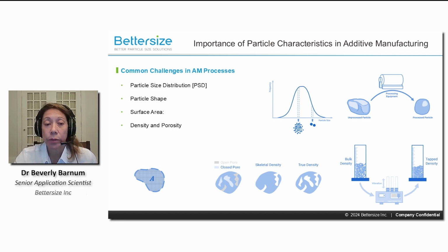The size of the powder particles affects the flowability and the packing density of the material. A narrow PSD, particle size distribution, may improve uniformity and layer deposition, while a broad PSD can enhance packing density for certain applications. Particle shape. The shape affects both the flowability and the behavior during sintering or melting. Spherical particles typically flow better and pack more efficiently compared to irregular or angular particles.